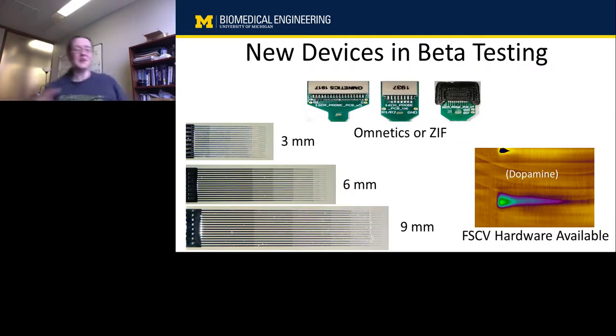So we're very grateful to the Brain Initiative for funding us to essentially work out all of our bugs and create a range of devices that are going to be useful to people studying brain areas all over the brain. So we finally settled on doing a 3 millimeter, a 6 millimeter, and a 9 millimeter device. So there's carbon fiber at the very tip. You can probably see that these shanks are gradually expanding silicon as we go up, and that silicon is there just to get enough support, for example, to get more than 500 microns into the brain. And that 3 millimeter device is really intended for recording from cortex, where it's just good to have some strain relief on the probes with that extra sort of millimeter or so.